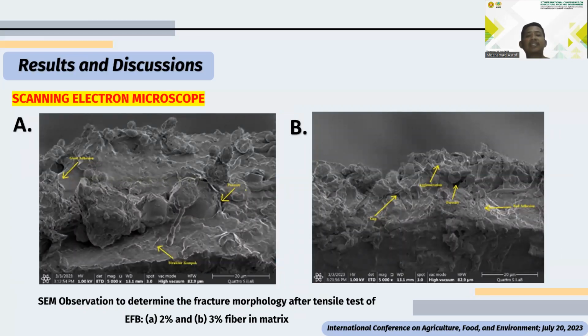So the tensile properties are also supported by the scanning electron microscope results. We know that in 2% there is good interaction with adhesion bonding between matrix and fiber. Conversely, in 3% there are many voids, many holes. We can see in the picture, with the label B, this is agglomerated fiber. So this is one of the factors decreasing the tensile strength of the composite.